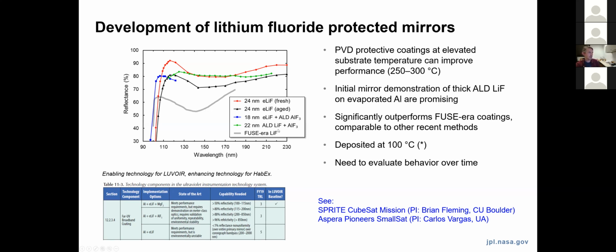We're also looking at an all-ALD approach to deposit the full lithium fluoride and cap stack at JPL. One possible advantage of the ALD process is that it maintains this low deposition temperature. Aside from LUVOIR, which is the flagship mission concept considering lithium fluoride coatings like this, which they acknowledge are at a relatively low TRL, there's also some upcoming CubeSat and SmallSat missions which are baselining this coating process.